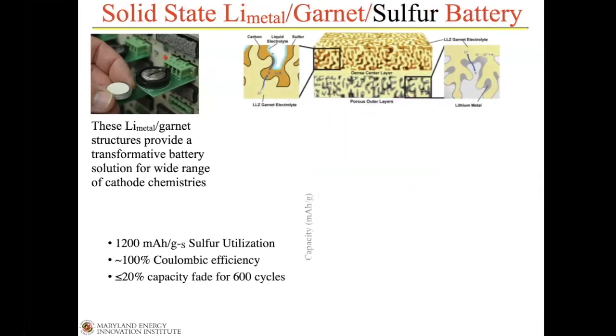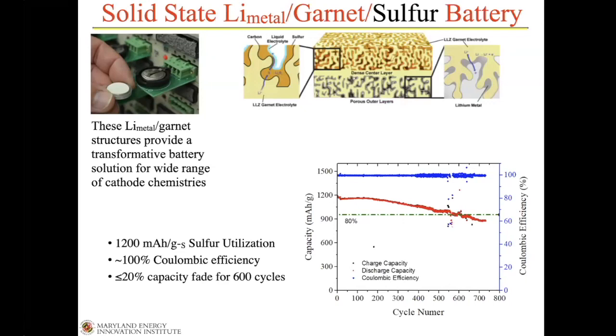Most of our work now has been done with lithium sulfur. We had a project funded by NASA where we did this. And so now we just fill sulfur, carbon for electronic conductivity, and a little bit of liquid electrolyte to help with the interface on the cathode side and lithium metal on the anode side. You can see how we can get about 1200 milliamp hours per gram because of the sulfur utilization we're able to get out of this. Again, great coulombic efficiency and less than 20% capacity fade for over 600 cycles.